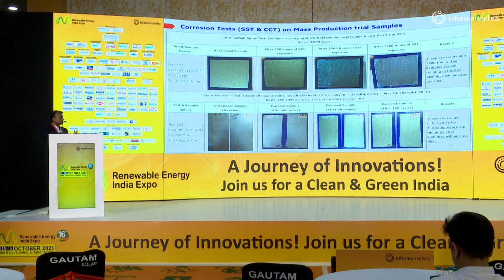The same was illustrated with the mass scale produced samples, where we performed the SST, salt spray test, in which we continuously spray 5% NaCl at 35 degrees Celsius. These tests are conducted as per various standards, for example, SST is conducted as per ASTM B117 or JIS Z 2371 or ISO 9227. Tests are being conducted as per these standards and have shown very promising results.